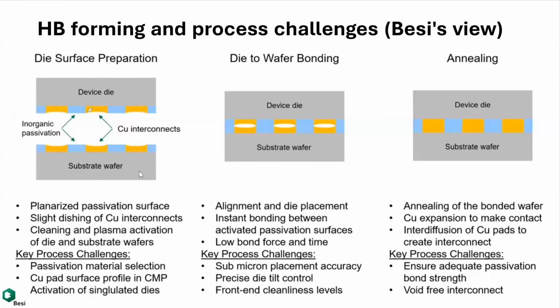Then so you need to do some treatments, forming some of the copper pillar, and more than that, of course. And then you bond them, and then the oxide here, that's from the process as well. All these had to be bonded perfectly. Okay, and of course they come with the various process challenges. We're not going to detail for now. Right. So basically, 3 steps: surface preparation before you bond it, then you bond, then you anneal to get rid of the void. That's pretty much the 3 simple steps that are related to the hybrid bonding. And that opens a lot of new doors.